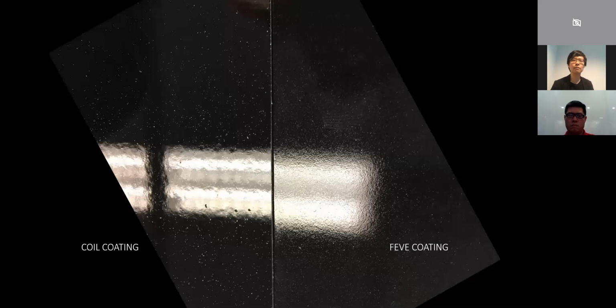So we went back to more discussion with Mr. Li about, okay, if that is not possible, what can we do? And through Mr. Li, we got introduced to another coating called the FEVE coating, which is not as good as a coil coating for what we want, but on the other hand, it is still better than a traditional PVDF coating in terms of reflections. So we went back to the drawing board and redesigned the details. The advantage of this FEVE coating is it allows the panels to be assembled first, and then you apply the coating on it.